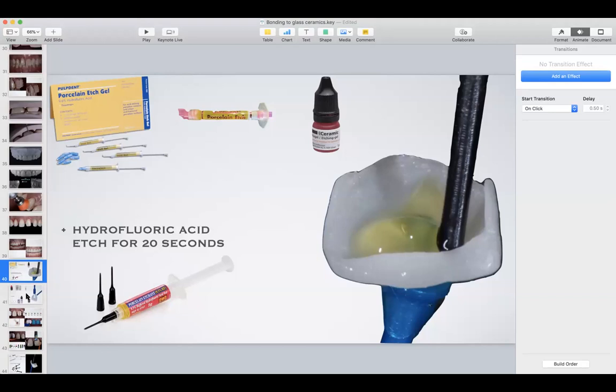On Emax, that's unnecessary, but on feldspathic, definitely you gotta do it, okay? But this is something that you can visually see. You can visually attest that you have those really opaque white spots on feldspathic. So you need to just get rid of those, all right? And you do that by applying hydrofluoric acid, scrubbing it in there for 20 seconds and then rinsing it. Your hydrofluoric acid is also included in your Choice 2 kit.